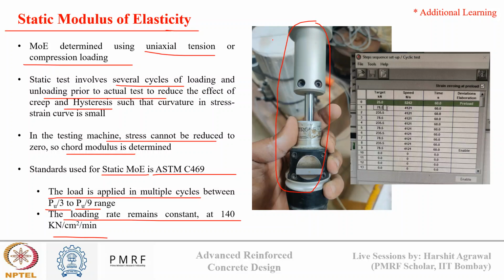So you see in the background there is a concrete cylinder kept at the top, and here you see an LVDT attached on the surface of the cylinder. And now from the top we subject cyclic loading cycles on the cylinder. So you see these cycles are set. This is a preload that we set, and then there are different cycles of load, PU by 9 to PU by 3, then again PU by 9, PU by 3, like this four cycles of loading we are subjecting at a constant rate for a constant amount of time.